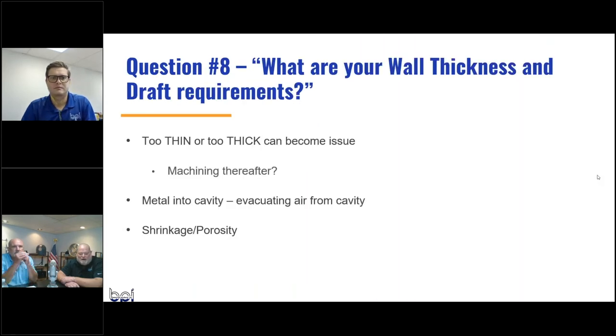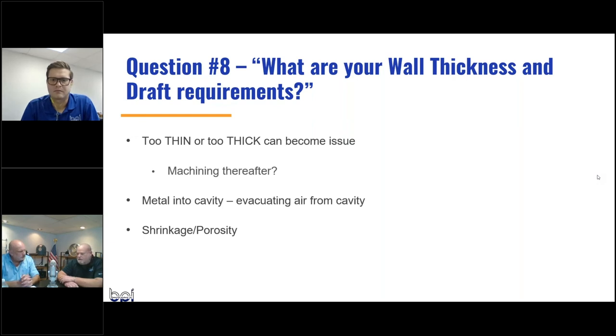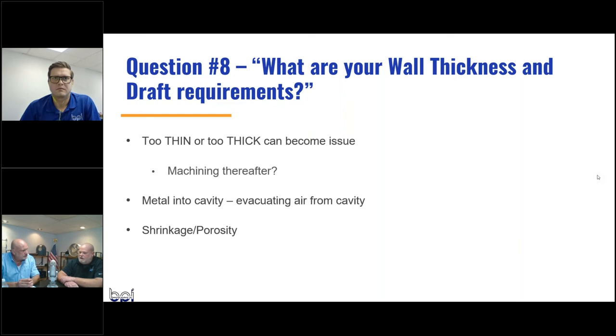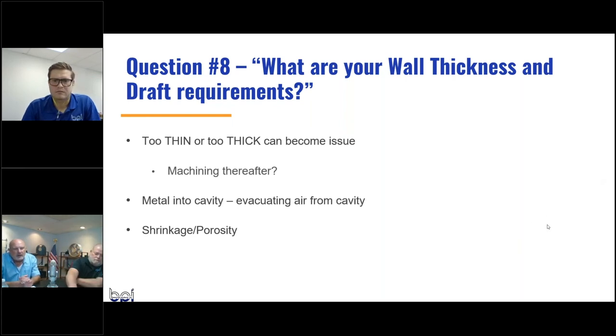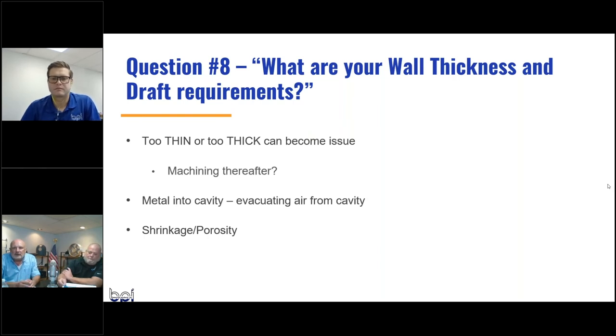Question number eight: what are your wall thickness and draft requirements? It can be too thin or too thick. You can come back with secondaries and sharpen a wall if you need it straight. The minimum wall thickness for permanent mold is about 0.180 inches. Why? It's gravity cast, so metal is cooling as it flows. To get a proper fill and evacuate the air, we need a minimum of about 0.180 inches, though we've gone down to 0.115 in different areas with secondary involvement.